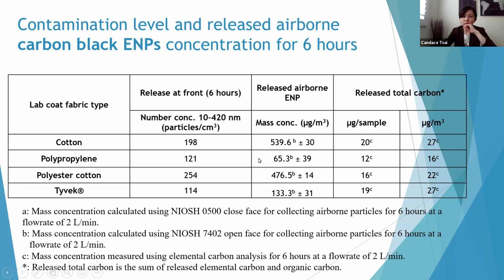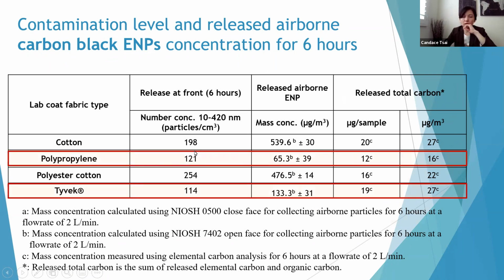Look at the data for the Tyvek and polypropylene - the airborne concentration we measure is much lower on these two types of fabric. However, the total carbon we measure is pretty high, based on my experience of many different types of sampling onto the carbon black and carbon nanotube. You can see this is 16 microgram per cubic meter and 27 microgram per cubic meter.